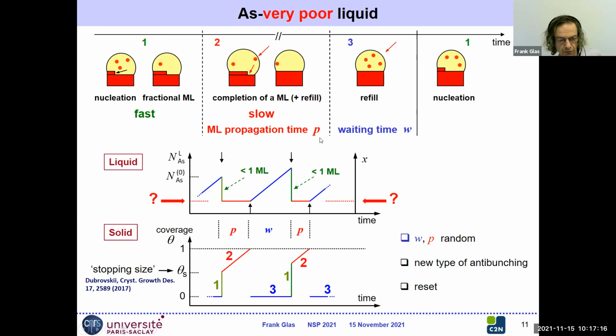Now let us look again at what it means schematically in terms of concentration. So at the bottom here, I reproduce schematically what we have measured. So stage 1, partial monolayer, stage 2, slower rate of progression of the monolayer until completion, stage 3, waiting time where nothing happens. So it's easy to understand this if we look now at the liquid. At some point, at some concentration of arsenic in the liquid, we have nucleation of a new monolayer, but we have not enough arsenic atoms or group 5 atoms in the liquid to complete a full monolayer. So our liquid gives to the solid everything it has to give, all the atoms of arsenic it can give, but this is not enough to build a full monolayer. So the concentration of arsenic in the liquid decreases, but by less than one monolayer.